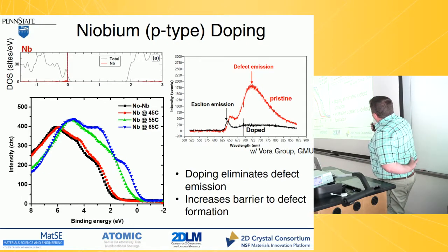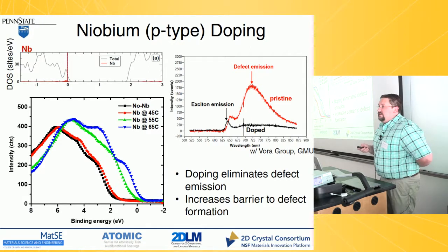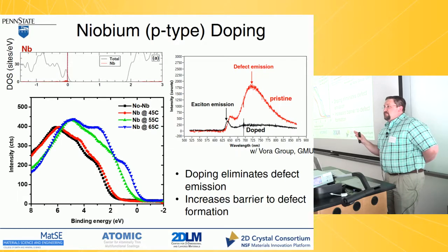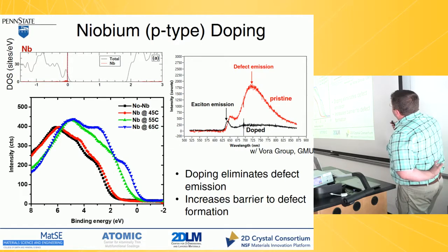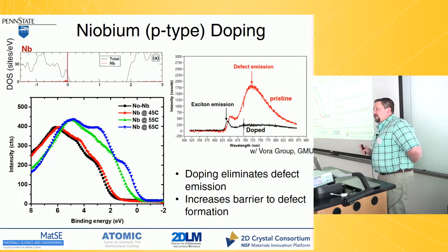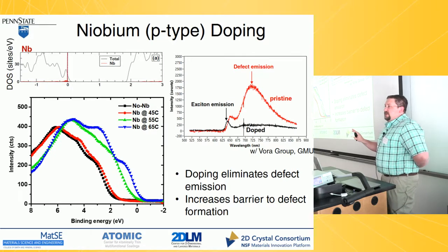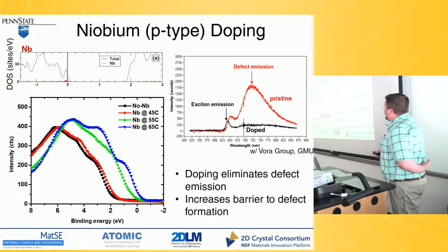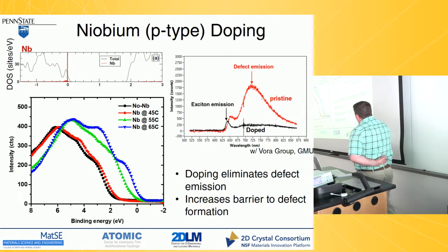It's very interesting. So this is at 5 Kelvin, I believe. So here's our exciton peak. You cool it down in a traditional one, you get this giant peak here that overwhelms everything. Almost every single person sees that, and most optical people hate us for it. But we've now doped this with niobium. We're not 100% sure what's going on, but the darn thing just disappears. So we need to better understand what's going on with this, but we were very happy with that.